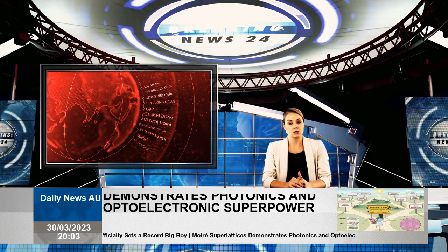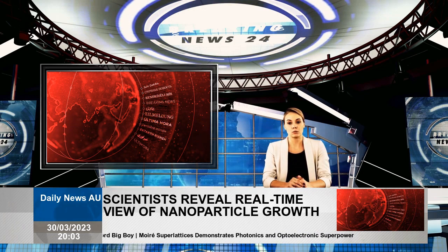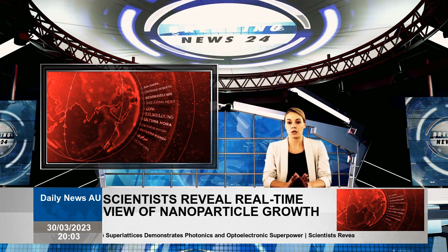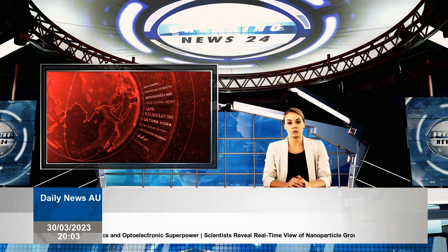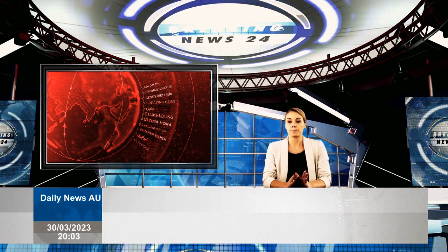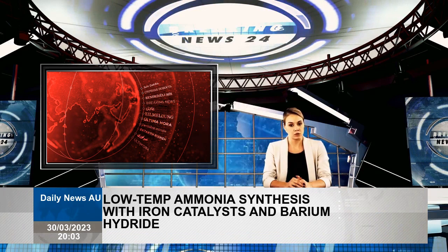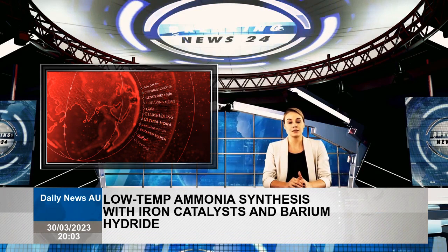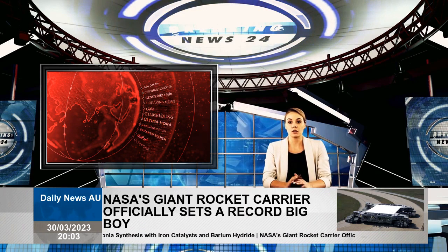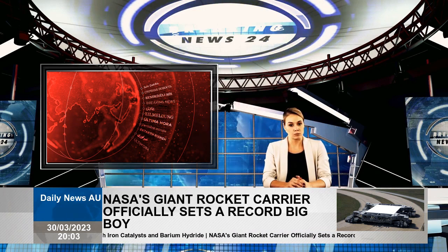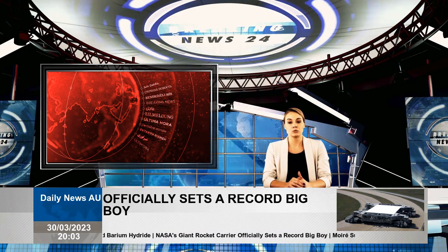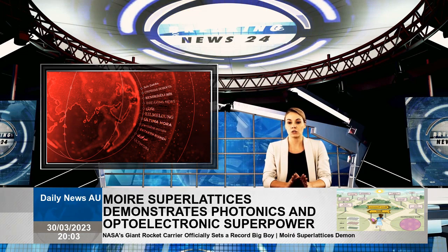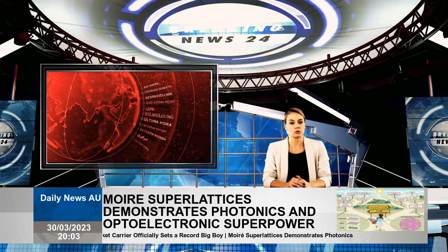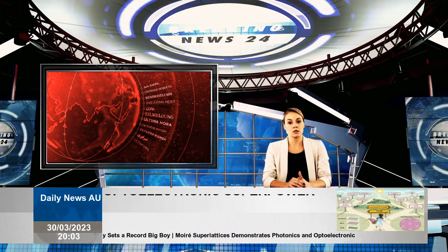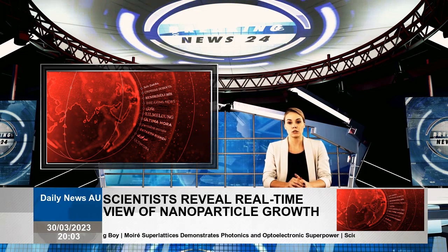A series of experiments revealed that the iron nanoparticles interact strongly with the hydride ions of both hydrides. As a result, hydrogen atoms move from hydrides to nanoparticles and desorb as hydrogen gas, leaving electrons behind. Hydrides donate these electrons to iron nanoparticles. It facilitates the dissociation of nitrogen gas into atoms, providing enhanced catalytic activity for ammonia production even at low temperatures.